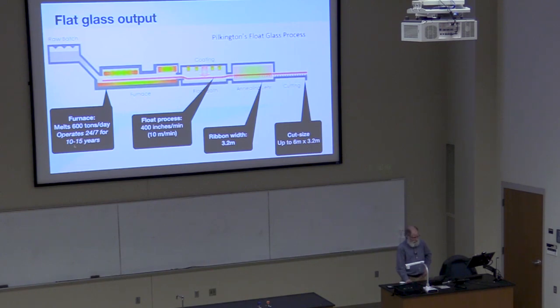So flat glass, just some numbers. The furnace puts in about 600 tons of batch a day. The furnace operates 24/7, 24 hours a day, 7 days a week for 10 or 15 years. Because once you build the furnace and you start heating it up, you can imagine the steel superstructure starts to expand, the bricks and the refractory change size a little bit. So you don't want to do that. So you heat it up once and you keep it there. As I said, the ribbon moves about 400 inches per minute, 10 meters per minute, 3.2 meters wide. For architectural glass, we might cut 6 meter by 3 meter plates. And then we would ship them to the window manufacturer, who cuts them down to whatever size they need. For automotive glass, you might have a smaller block size here that would then be cut down to the windshield size.